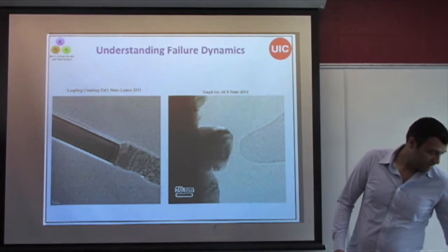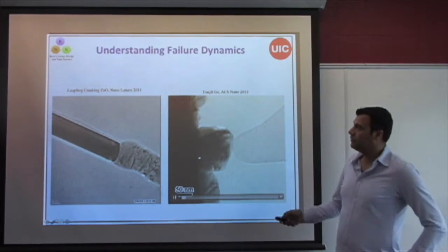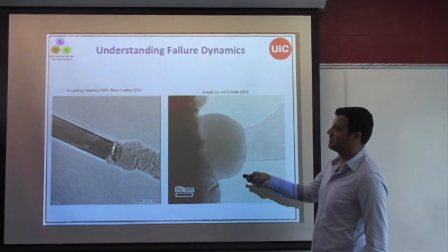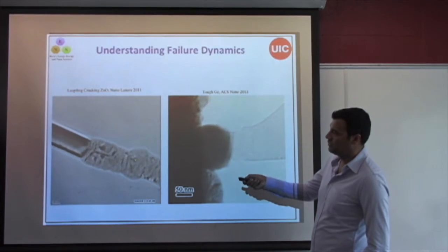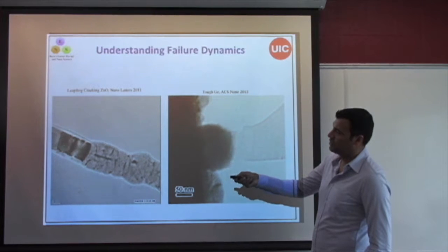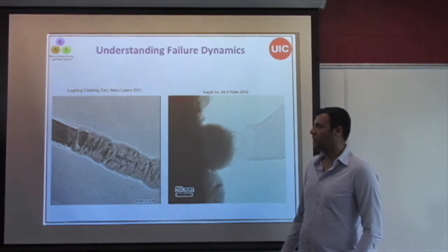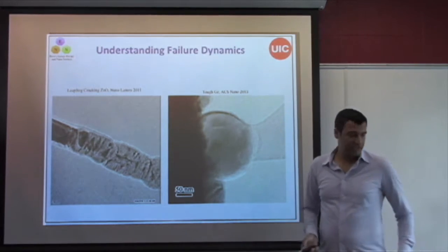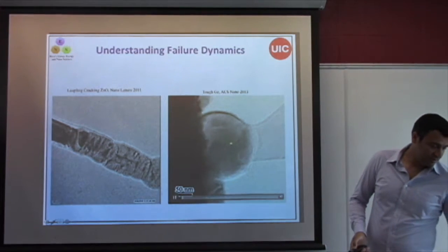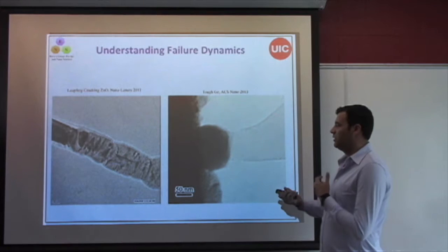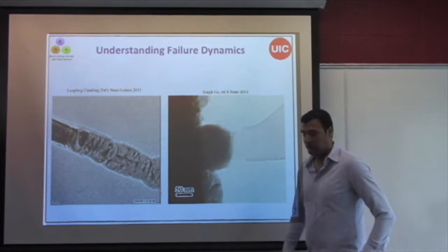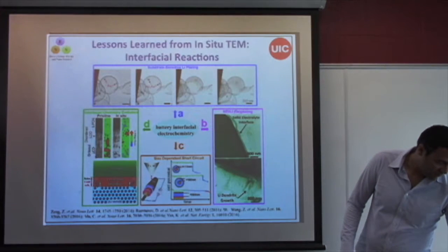These videos are showing examples of failures and behavior of different electrodes. This is zinc oxide. If you notice, this material goes through quite interesting failure during the progress of lithium in the sample, which typically starts with the formation of some cracks in a particular orientation, and then lithiation of the rest of the structure, which involves the conversion reactions. This is an example of germanium, basically metals that we see. It shows quite plastic and very tough behavior under various lithiation and delithiation dynamics that we can now quite visualize for further analysis.